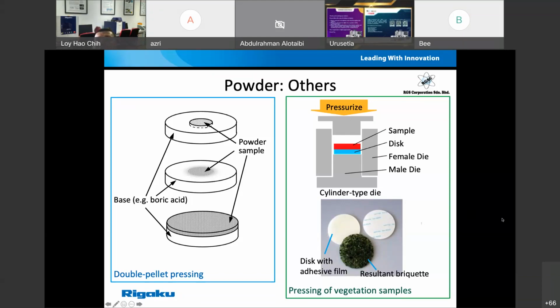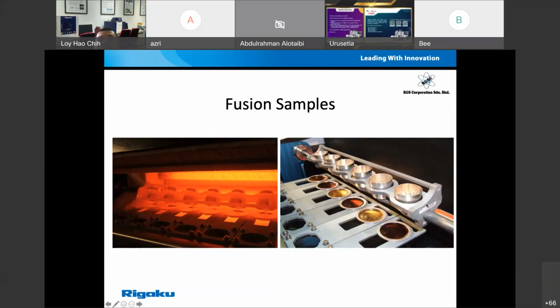So another, I'll say, very famous way to process your powder samples, especially for geological samples, is by fusion. Okay, fusion is a process where we melt your samples, or we digest your samples, with a lithium borate flux, where your samples will be digested inside the lithium borate flux at a very high temperature, a 1100 degrees Celsius furnace. Once your samples are digested inside the flux, we pour it out into a casting disc or casting plate, and the sample will cool and form a bead we call a fusion bead, or a glass bead. Okay, it's something similar to glass.